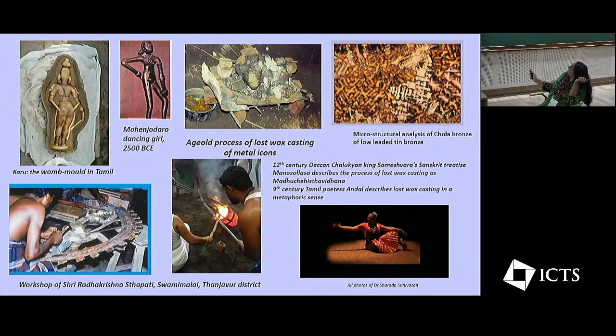And in the interdendritic space, you also see some of these blackish patches, which is because if you just take copper and add tin to copper, one of the problems is that there are some problems in casting it because of the freezing range and so on. But the addition of lead, because lead is a kind of soft material which flows into the grain boundaries and all that quite easily. It's a low melting metal and so on. So the lead sort of fills up these crevices, and so you get a better casting. So that's why rather than just using pure copper, which also has some problems with casting, or just bronze, which is just basically tin and copper, they were also adding some lead to get a better casting. So this is what we call low leaded tin bronze.